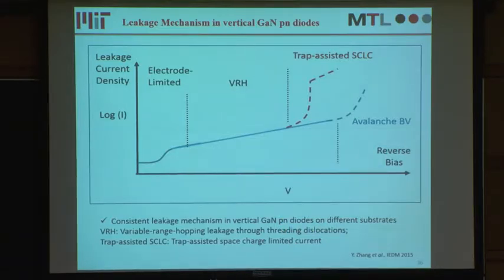And if the structure has some defects, then at some point there is a trap-assisted space charge limited current that will turn on. This trap-assisted space charge limited current will determine the leakage path, the leakage mechanism, and the breakdown behavior. And if the device is really good, without much defects or dislocations, this variable range hopping will continue until the onset of avalanche breakdown.